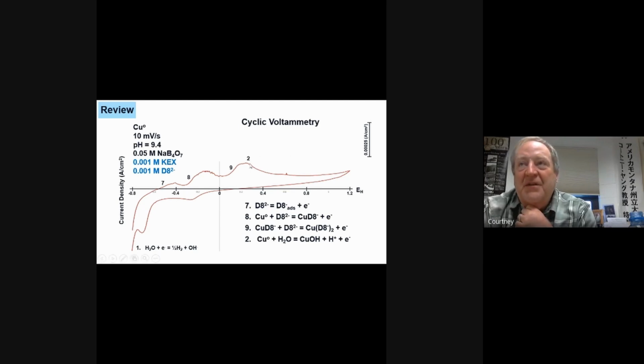We see this peak here, and we sort of see a peak here. Ignore this guy. It was just an artifact. I think we had a lightning strike during this, and we saw a little spike in the voltammogram. Didn't ruin the study. It's just that it happened. And then, of course, as you continue to go, you start to see more current because of oxygen evolution. So xanthate is present, and yet D8 reactions are occurring, which tells you that D8 is masking what the xanthate does.